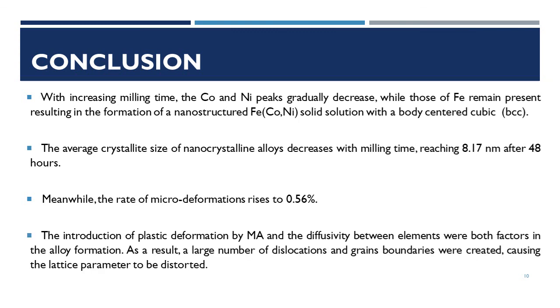And the introduction of the plastic deformation by mechanical alloying and the diffusion between elements were both factors in the alloy formation. As a result, a large number of dislocations and grain boundaries were created, causing the lattice parameter to be distorted.